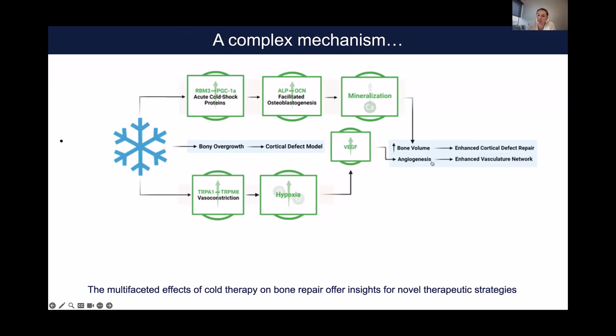But we saw as well angiogenesis was stimulated. And it was difficult for us to prove why, because we couldn't figure it out. So we measured the hypoxic cells upon cold exposure, and we saw a drastic increase of hypoxia near the injury site upon cold. And that was associated with an increase in VEGF, but as well in a marker for endothelial cells, the CD34. And we saw that these two things were in conjunction with a modification of the vasomotor tone through TRP-related pathways, okay, which are transient receptor potential channels.